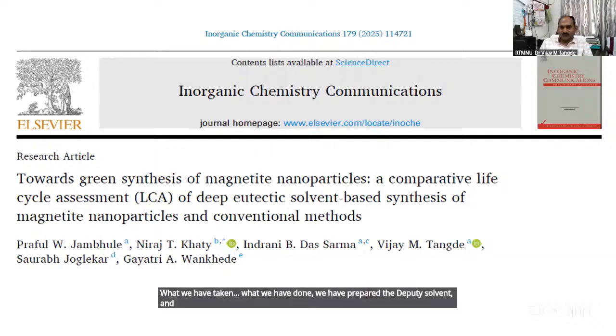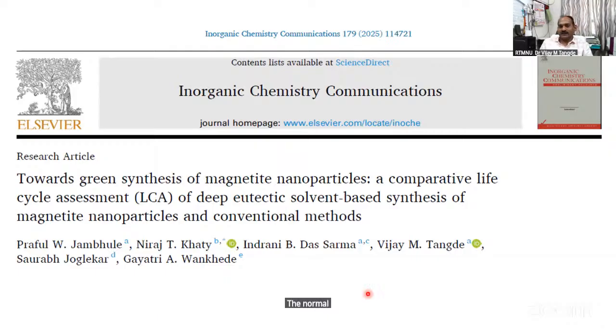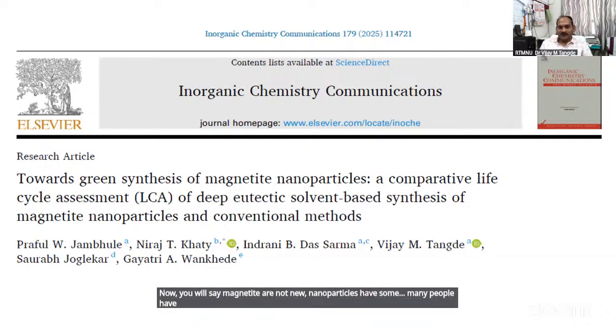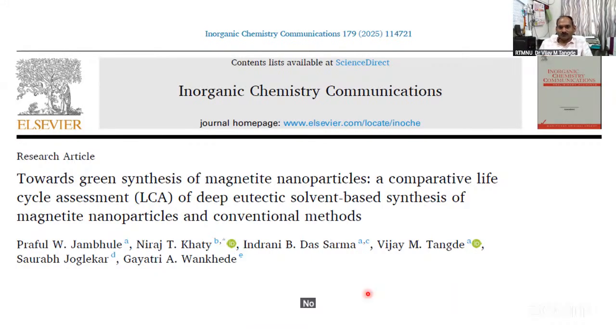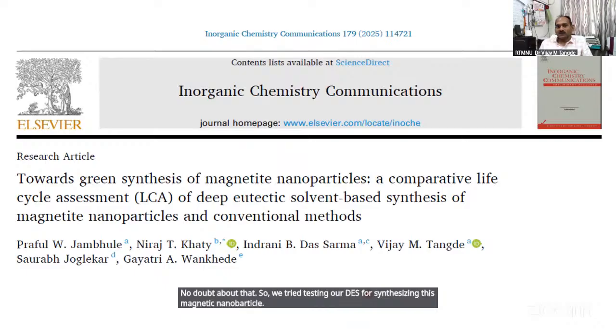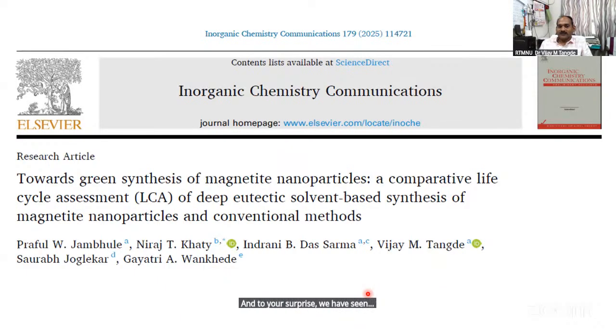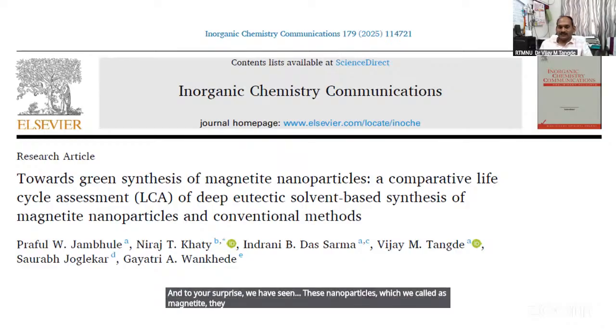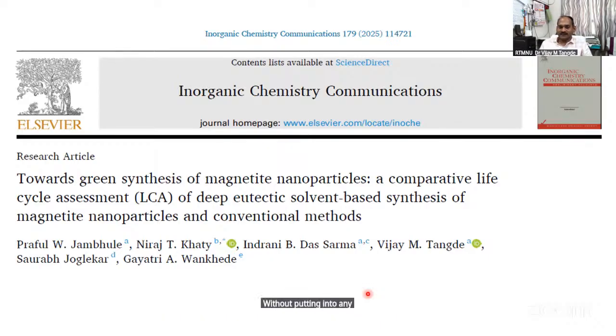So in such a case, we have prepared the deep eutectic solvent, and based on the deep eutectic solvent, we have tried to synthesize ferrite nanoparticles, which we call magnetite. Now you will say magnetite nanoparticles are not new. Many people have prepared them by the solvothermal method, the Sol-Gel method, the co-precipitation method. There are n number of methods, no doubt about that. So we tried testing our DES for synthesizing magnetite nanoparticles. And to our surprise, we could synthesize these magnetite nanoparticles with ease, without putting in any external effort.